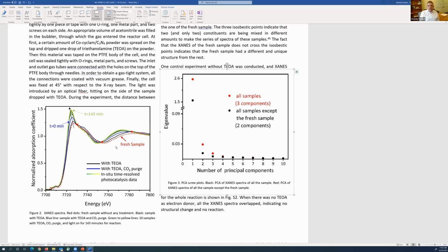But in those cases with nanomaterials, you usually can't, because principal component analysis requires some kind of standard that you rotate your basis of components to match. But you don't have standards in the nanomaterial world. They are all non-bulk like. And you cannot use theoretical standards. So here we're lucky, but in principle, there is a method called MCR-ALS. And that method allows you to objectively, without any prior knowledge, or with minimum prior knowledge, to get the spectrum.